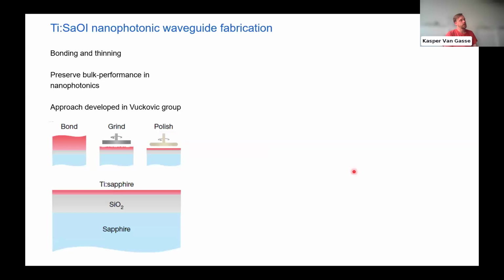So why bonding and thinning? This is something that was strongly developed in the Vuckovic group. Originally this was developed for quantum materials where you cannot accept the defects introduced by smart cut. When you do smart cut, you implant at high energies, and you create a lot of defects.